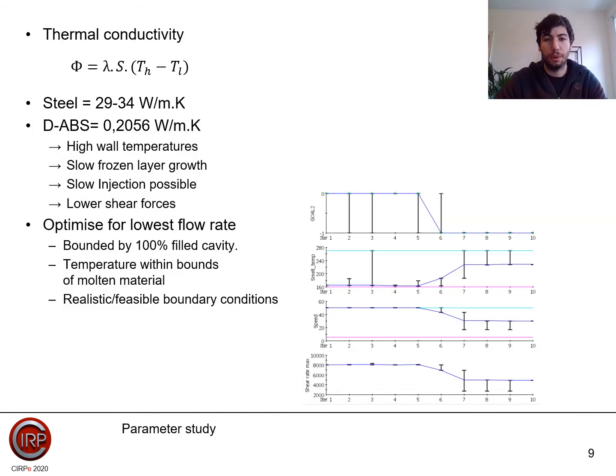The injection molding parameters, such as cooling between shots, injection pressure, temperatures, and hold pressure, that have to be used in combination with plastic molds, differ significantly from conventional injection molding due to the vast difference in properties. This is illustrated by choosing one variable, thermal conductivity.